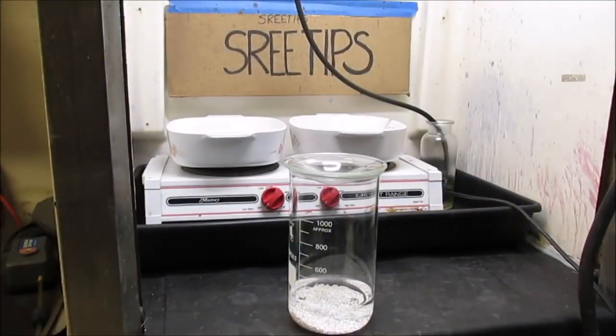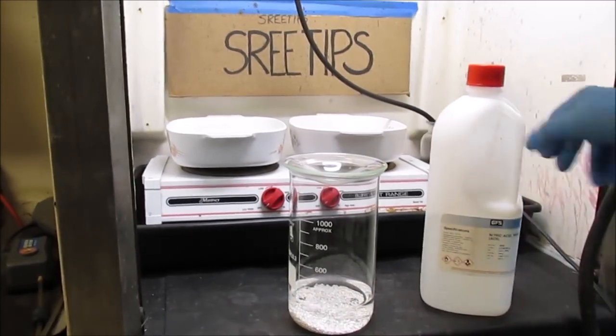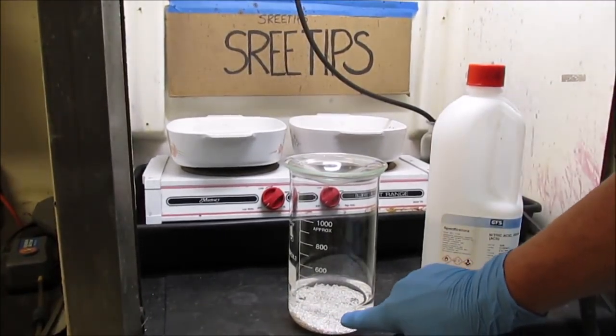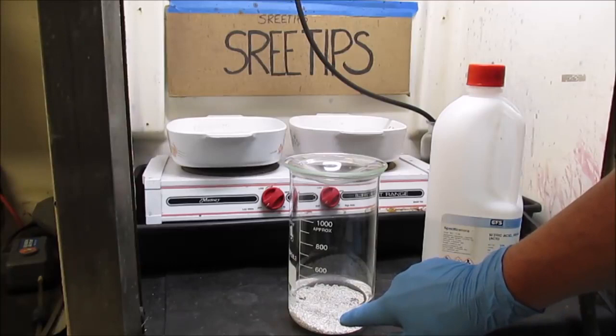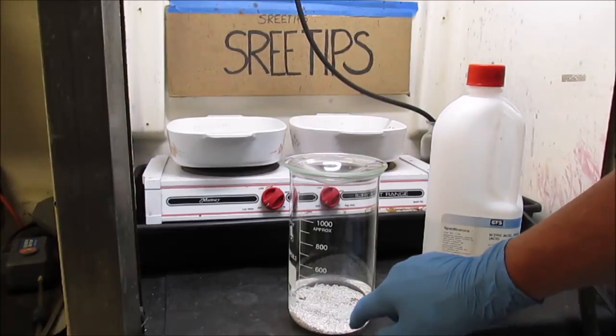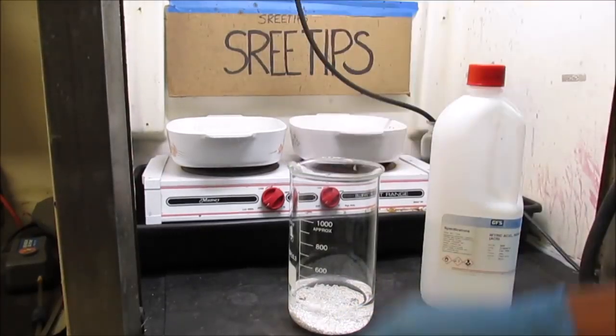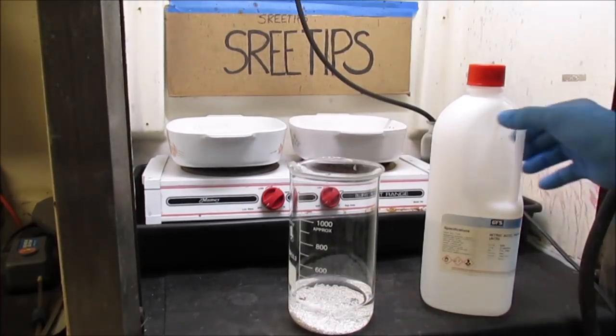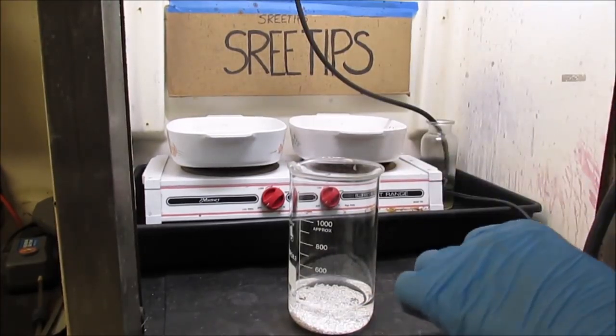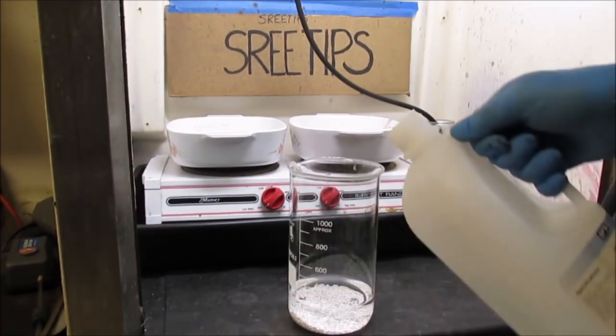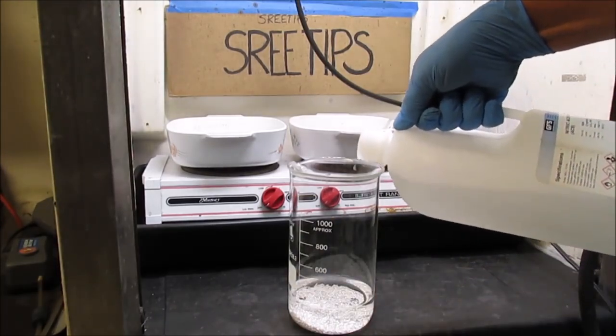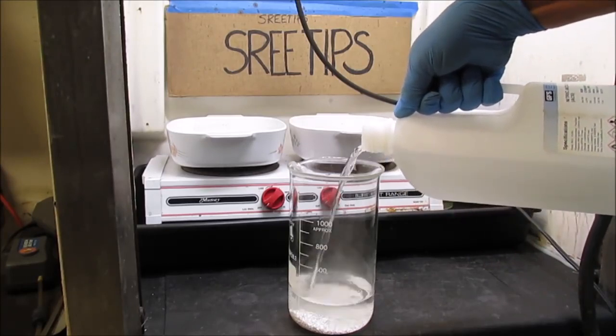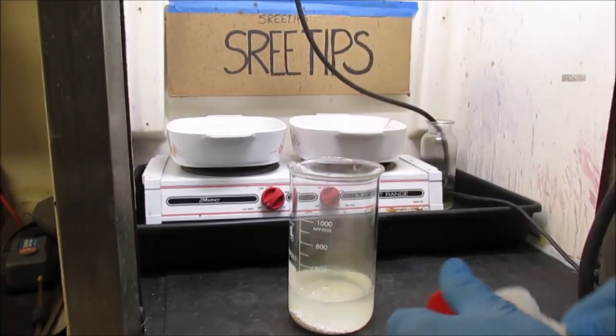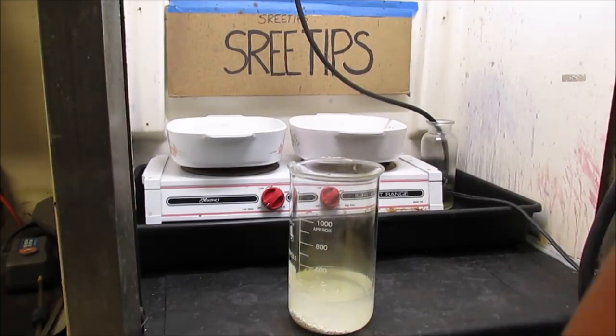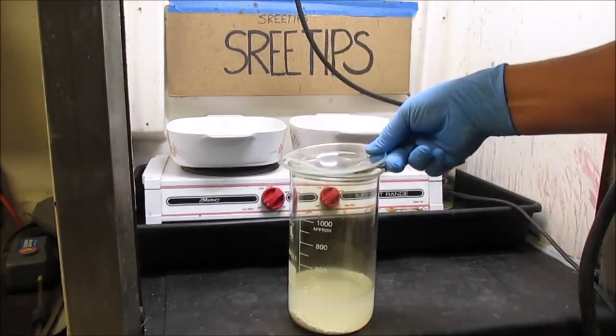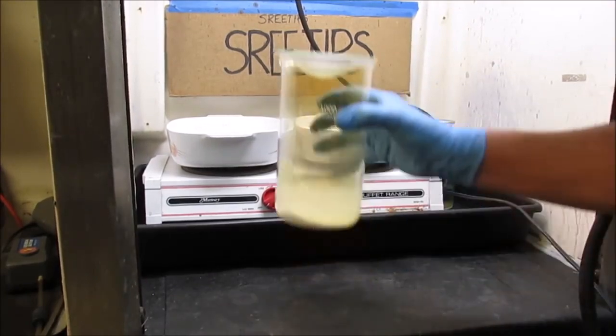What I want to do here is slowly add nitric acid to this. Remember to use distilled water here. I can't use tap water because it has chlorine in it. The chlorine will mix with the silver nitrate and form silver chloride, which is something I want to avoid. Right now I'm going to add about 50 ml of nitric acid to the silver. I'm going to cover it up here, and we're going to put it up on the heat and let it dissolve.